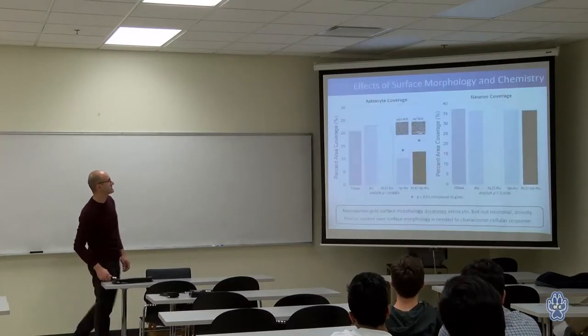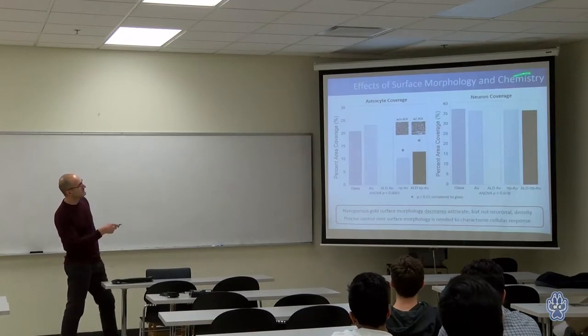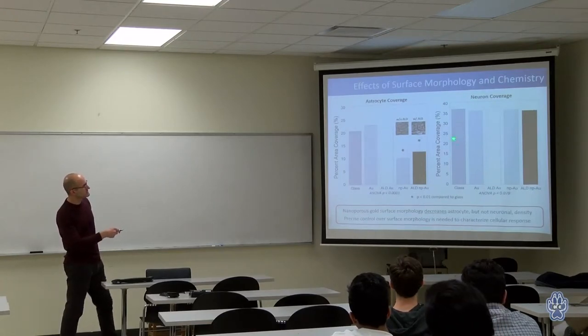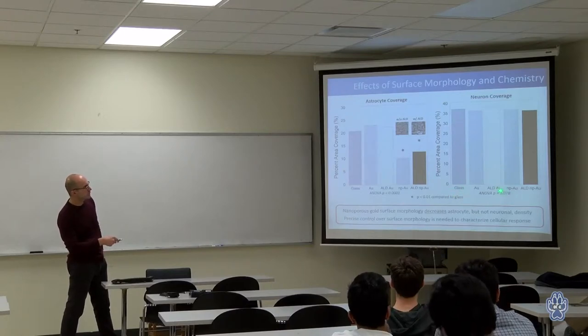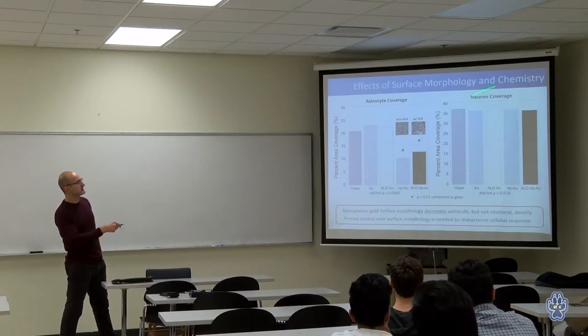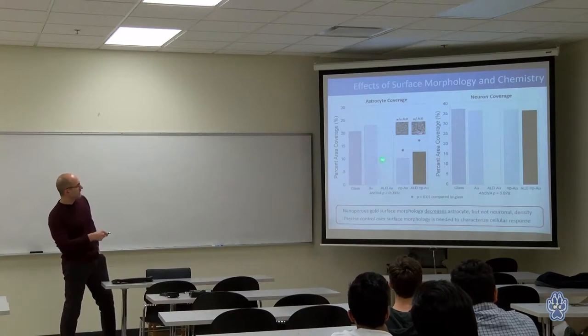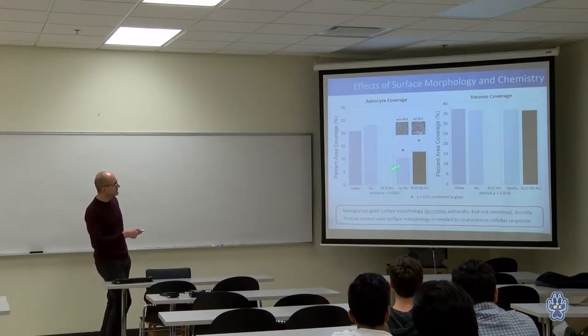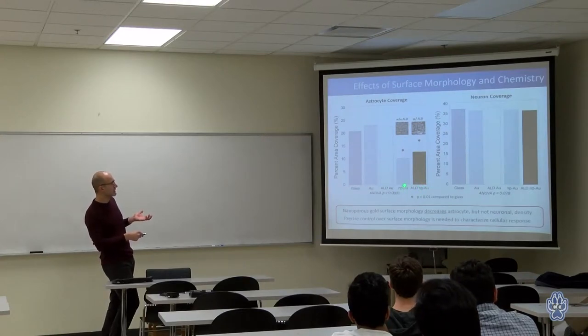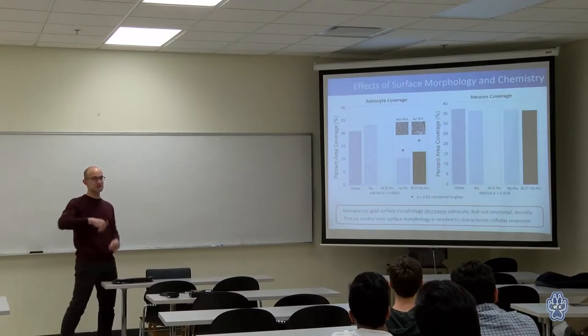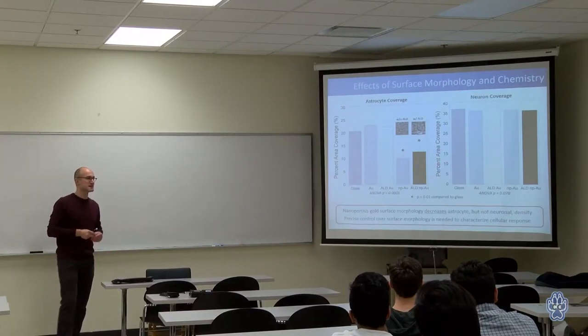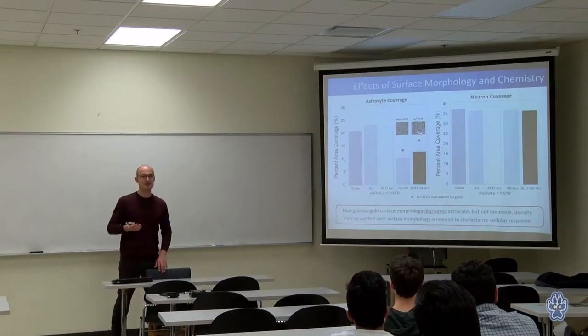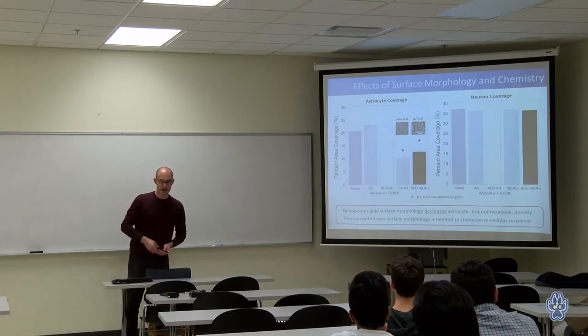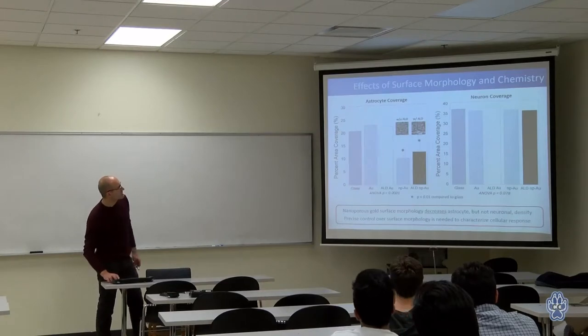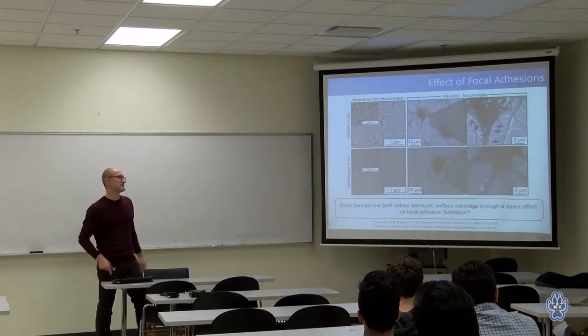And when you do this, you basically see, so this is a little bit crowded here, but these are the neuron coverage, percent coverage on a surface. You see that whether it's glass, gold, nanoporous gold, or that insulator shell on it, there is no difference between them. But if you go to the astrocytes, the cells that we didn't want, with nanoporous gold, whether it's coated with that thin insulating sheet, aluminum oxide or not, you still have that reduced spreading, which is actually good news, because now it suggests that it's not a toxicity effect, but it's actually the topography that guides how a cell attaches onto the surface.